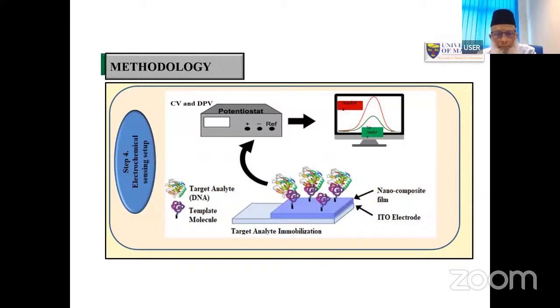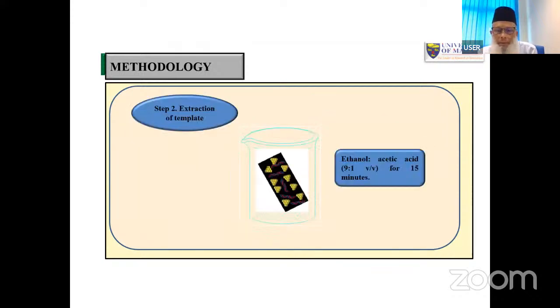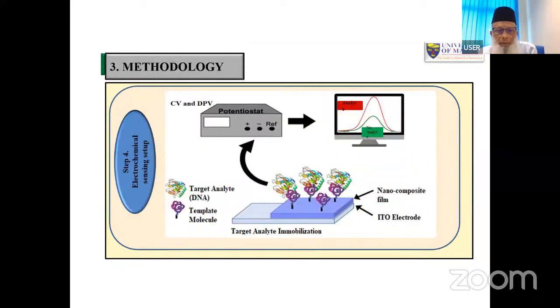Later, it was used for taking the real sample, and we found that the pork DNA came to this position again, giving us the peak, meaning that it's working. And if we took any other meat, like chicken or buffalo, it didn't match.